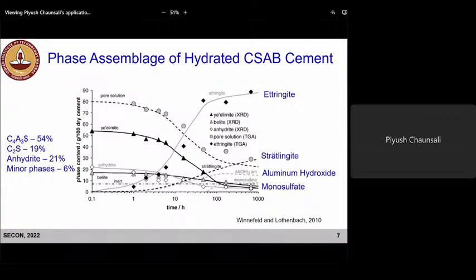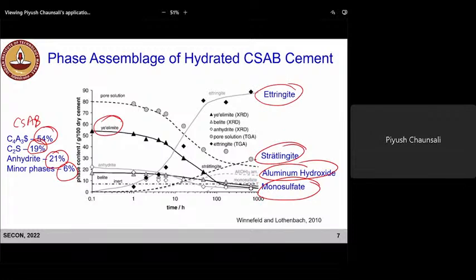This figure shows how these phases evolve with time. In this case, this is the CSAB cement which had this phase composition: 54% yeelimite phase, 19% belite phase, anhydrite, and then some minor phases. And when we add water to it, what happens? So yeelimite hydrates, so you can see the reduction in the amount of yeelimite with time. All these phases are reacting, and what we are seeing is the formation of phases like ettringite, stratlingite, aluminum hydroxide, monosulfate. So these are the phases which we just discussed in the last slide. These are the primary hydration products which are formed during the hydration of CSAB cement.